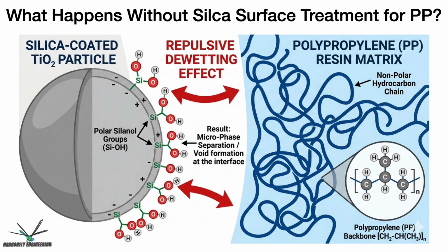So let's just pretend for a minute that the functionalization of the silica-coated titanium dioxide particle was forgotten or left out. What would happen then? The silica surface has a polar hydroxyl OH group that would repel the long hydrocarbon chains of the polypropylene matrix. This repulsive dewetting effect would result in a separation or void formation at the silica-polypropylene surface. There would be an increase in processing temperatures, high shear, and pigment clumping. Overall, not a good situation.